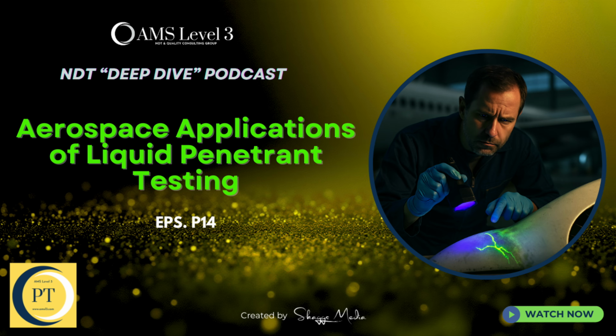Because the goal isn't just to find the tiniest possible crack, it's to maximize detection reliability without getting an excessive number of non-relevant indications. The forming processes for these exotic alloys often create surface features that a level 4 penetrant would flag, but that are structurally irrelevant. Tuning this sensitivity lets them find the critical flaws while minimizing the false positives. That is an incredible level of control.